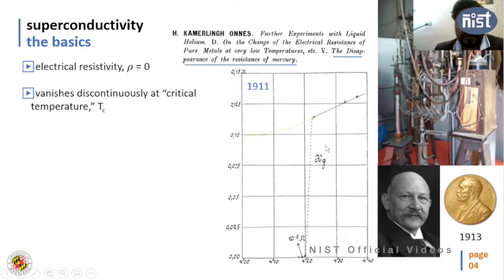So if you measure a conventional metal, assuming there is nothing else, the resistance as a function of temperature would look like these dotted lines. So it should follow this line. But instead of doing that, suddenly some sort of discontinuity was observed around 4.2 Kelvin. And this is something different, a phase of this metal, which is known as a superconducting phase, or superconductor.